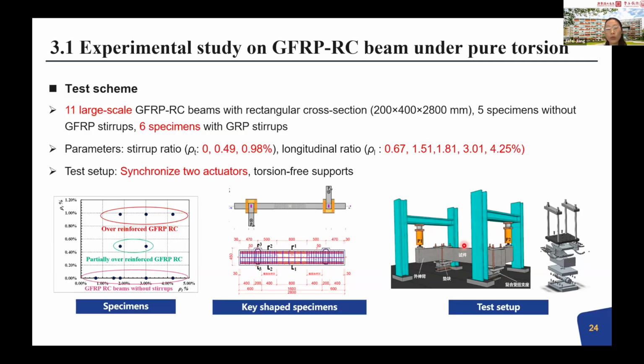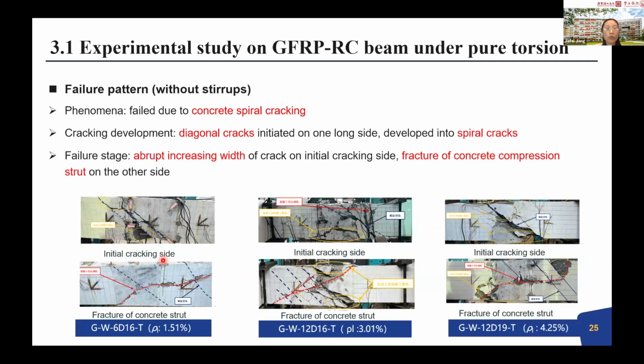So make sure the pure torsion is exerted on the beams. And also, we know that for FRP-reinforced beams, because FRP is elastic, there will be over-reinforcement or rupture of FRP. So here we designed the beams under torsion following these three different categories of failure mode, and we also realized these three failure modes in our final test results.